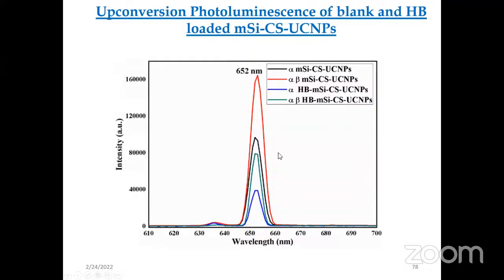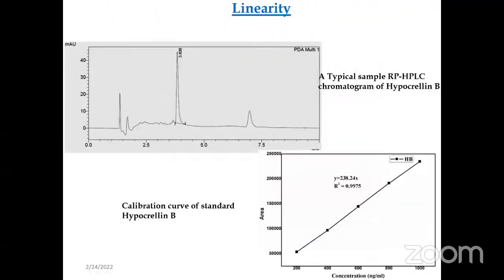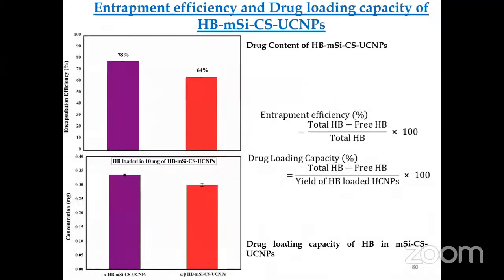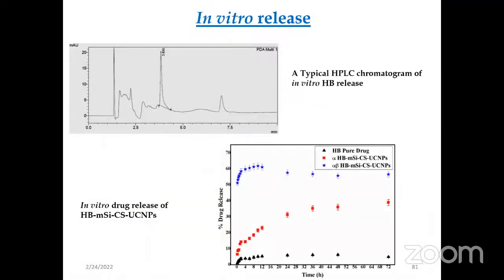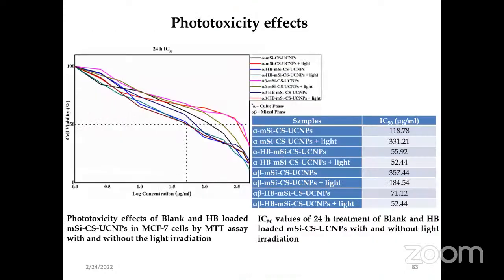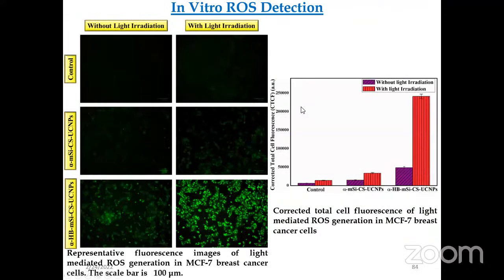Again, we also took photoluminescence to show whether the alpha, the mixed phase or the single phase shows better efficacy. We quantified the amount of drug entrapped, and we also studied the release pattern. We could show that phototoxicity will be higher on exposure to the light source compared to without light.